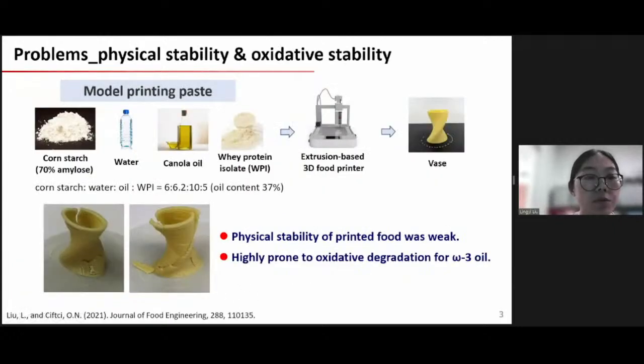In our previous work, we developed a model printing paste containing high content liquid oil. This printing paste can print the three-dimensional shape vase here by using an extrusion-based 3D food printer. The remaining problems: one is the physical stability, because normally the shape will be broken after several hours of printing. And the other concern is about the oxidative stability, especially when we use omega-3 oil.